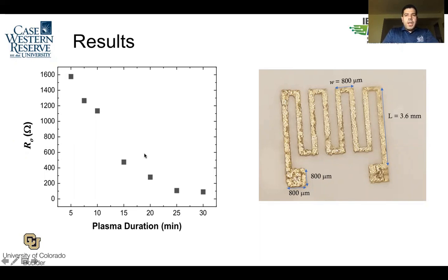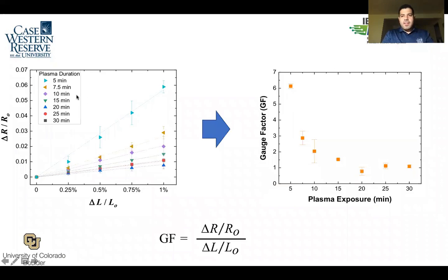And then we wondered, why shouldn't we test the gauge factor at each plasma duration, what will we get? This is what we got. Here you have a curve, normalized change in resistance versus strain. The plot on the right-hand side is merely the slope of this curve, which is the gauge factor. So the gauge factor here at 5 minutes is equal to 6, and it decreased exponentially, as was the case with resistance, and you see it plateaued after 20 minutes.